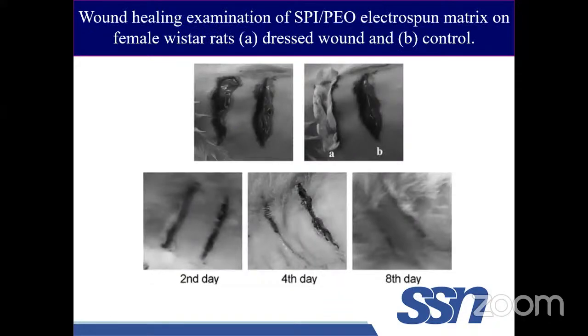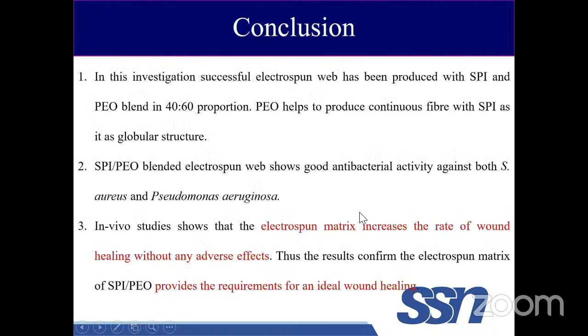Further, we tested against female Wistar rats by creating a wound in the rat. Two wounds of similar size were created, and one wound was left as such to heal, and the other wound was dressed with the nanofibrous dressing material that we prepared. As you can clearly see from day 2, day 4, and day 8, the wound healing was much faster in the nanofibrous dressed material compared to the open wound. On the 8th day, the wound has been completely covered, and we can clearly see the hair starting to grow, right? From this investigation, we conclude that SPI-PEO was successfully prepared as a nanofibrous matrix, and the prepared nanofibers showed good antibacterial activity against both gram-positive and gram-negative bacteria.